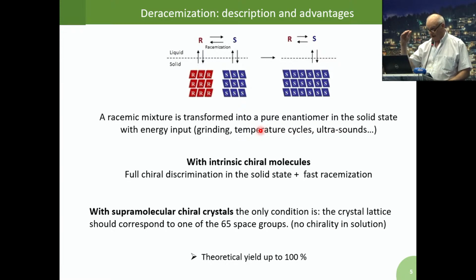You increase temperature by 10 degrees and then you decrease slowly and you repeat that cycle. Or you can add ultrasounds also, and then you will have an irreversible evolution of your system towards homochirality in the solid state and always a racemic mixture in the solution or the molten state. So this is a very important discovery because this could explain maybe the spontaneous evolution towards homochirality, so the first step towards life. If now you have a supramolecular chiral crystal, what does it mean?